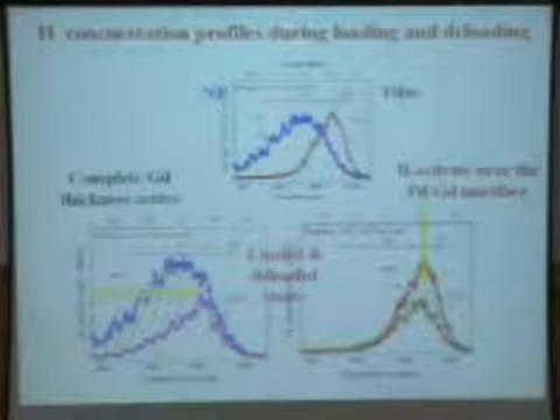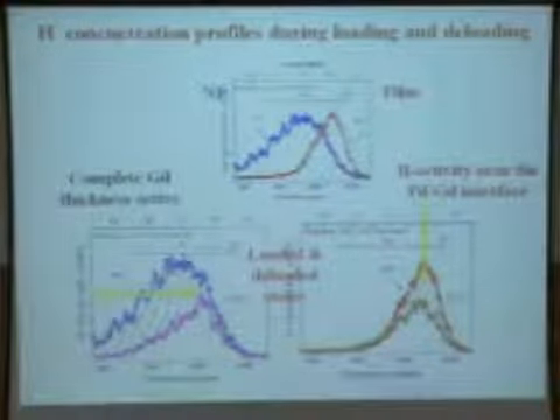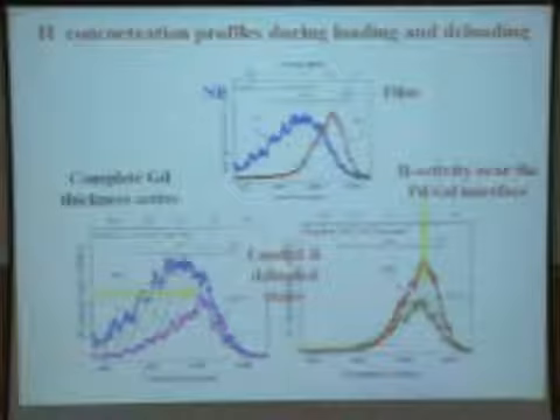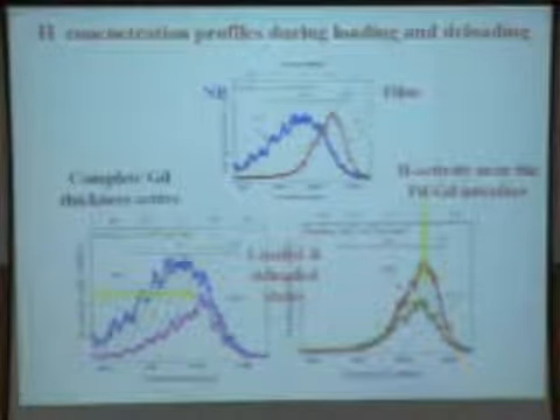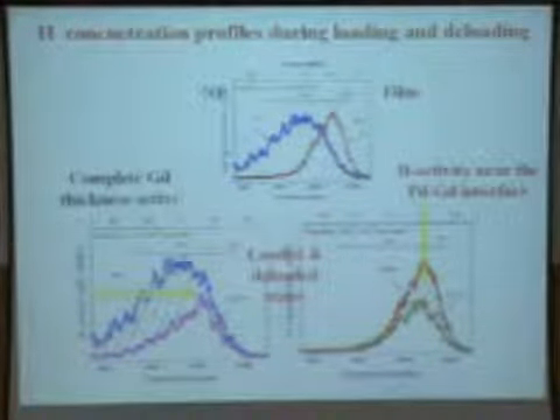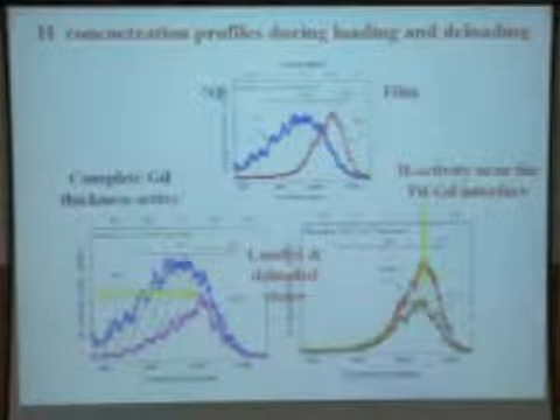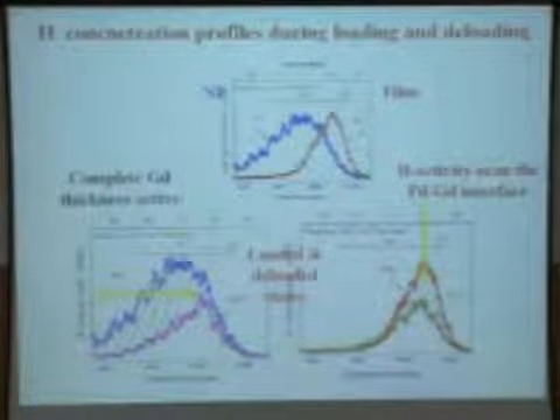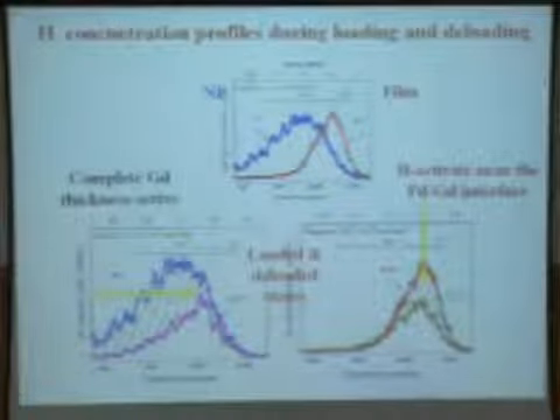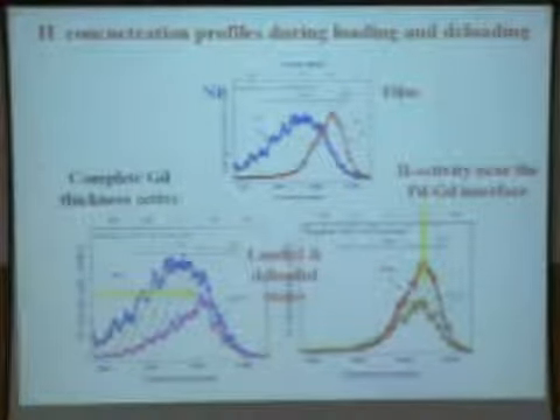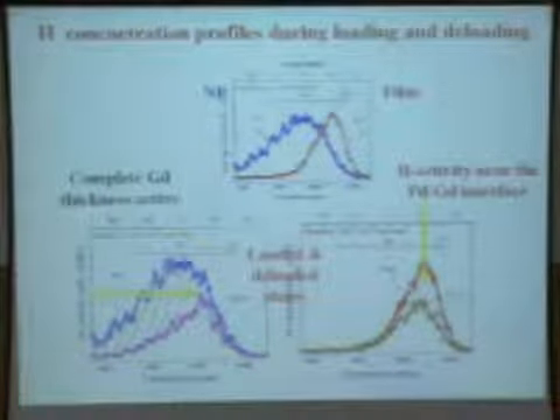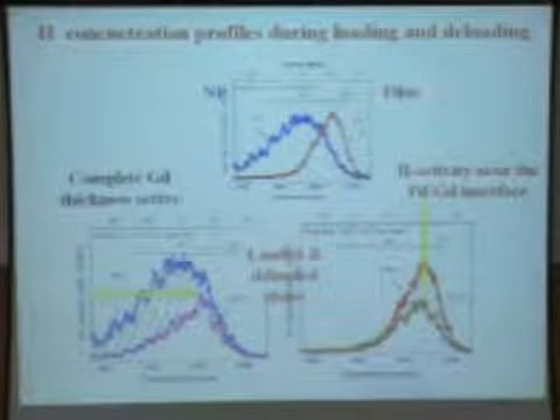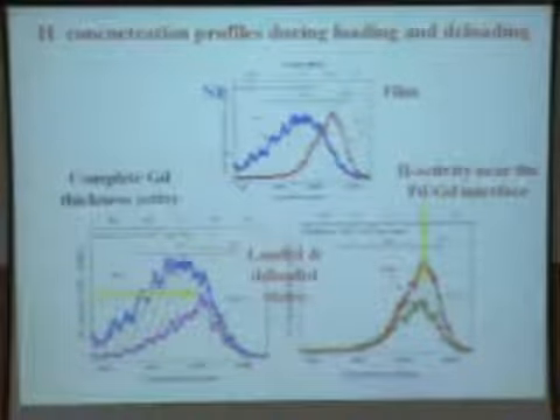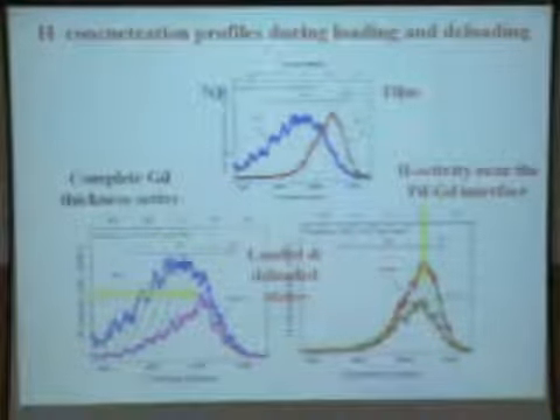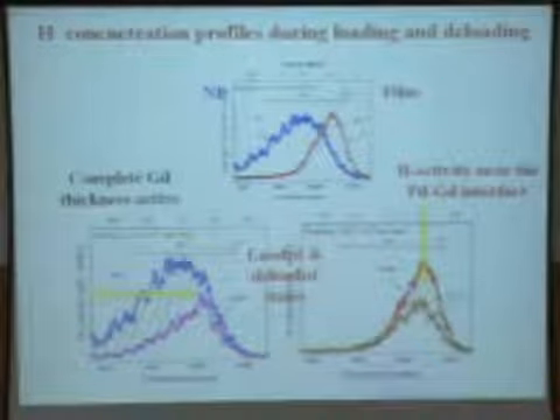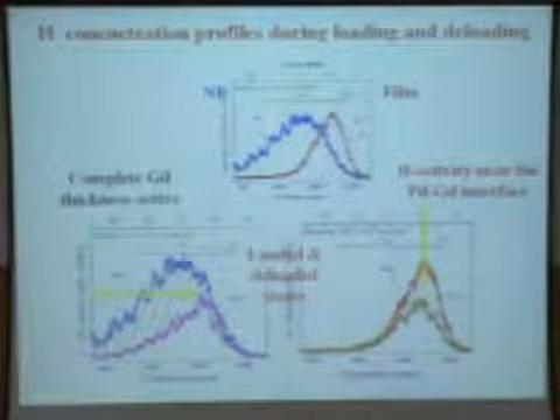Okay, but before I go further, let me tell you how we were making this nanocrystalline layer. You must have noticed that while describing the results, I only compared thin films with the nanocrystalline layer. I did not change the crystallite size, because in our technique it was not possible to change the crystallite size. Thin films were being prepared by a vacuum evaporation setup, and what we did, we created the vacuum, and then we introduced an inert gas. And this is called the inert gas evaporation method. This is a very simple method.